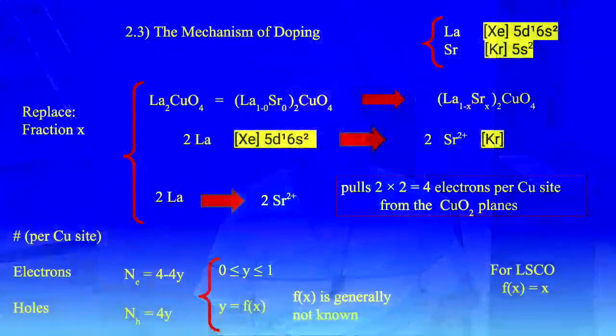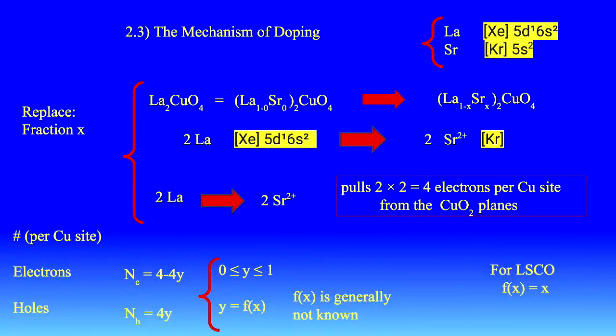So the mechanism of doping: take LSCO as an example. You start from the parent material, which is lanthanum 2 copper oxide 4. Now, lanthanum is 6s2, and strontium is 5s2. But if you replace lanthanum by strontium 2 plus, strontium 2 plus is lacking 2 electrons. So what happens is that it pulls these 2 electrons from those oxygen orbitals, creating holes. And that's how the holes are introduced in the copper oxide plane.